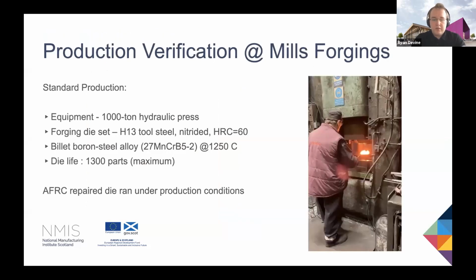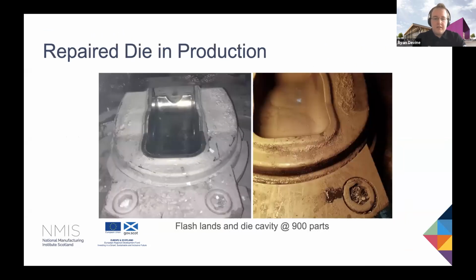So for the production trials at Mills Forging, they had a 1,000 ton hydraulic press, and they would normally expect to see 1,300 parts out of a new die. And our die just ran in the exact same production conditions that would normally happen. And this was then carried out at their centre. So these pictures were taken in their press after the die had produced about 900 parts.